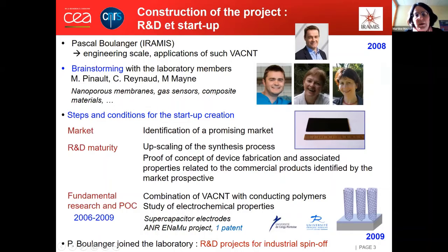At this time, we had only small samples, basically 2 centimeters large. So we went to the upscaling of the synthesis process in order to get higher surface samples. And then we had to get proof of concept of device fabrication and to measure the associated properties of this device, related to the commercial product identified by the market prospective. And in the end, it turns out that the market prospective identified a field around energy storage, basically supercapacitors, so supercapacitor electrodes.